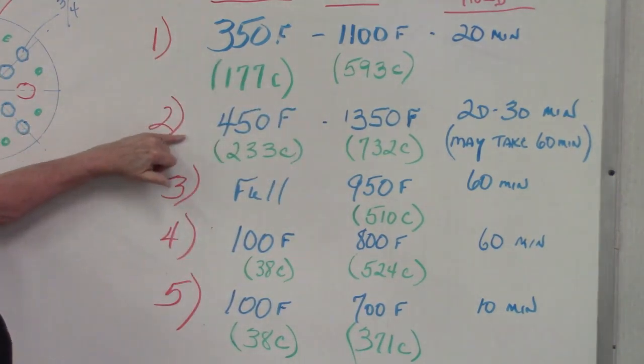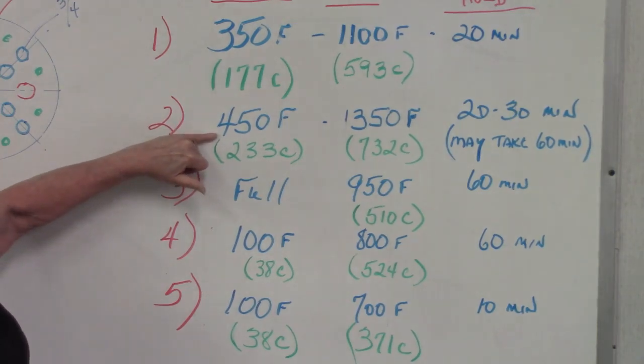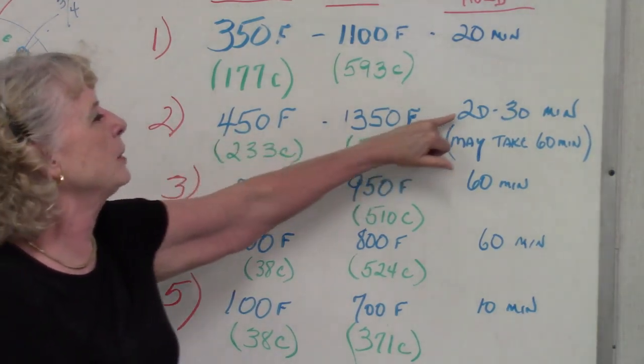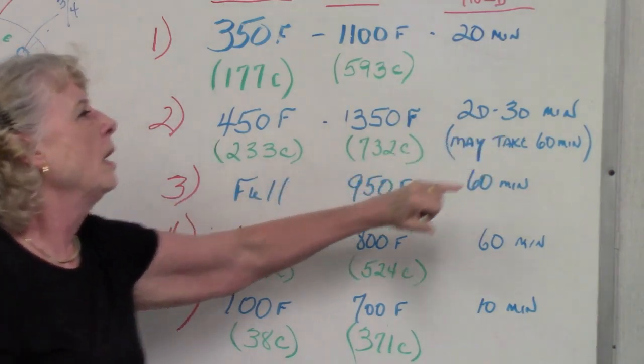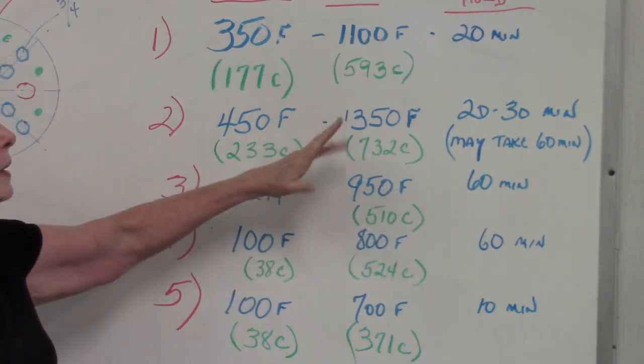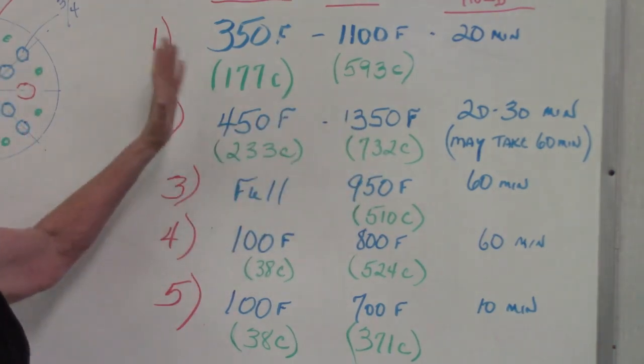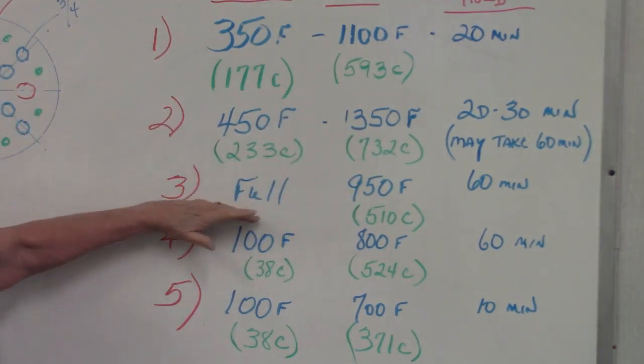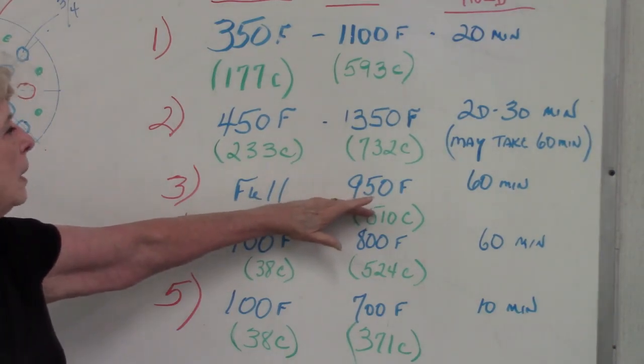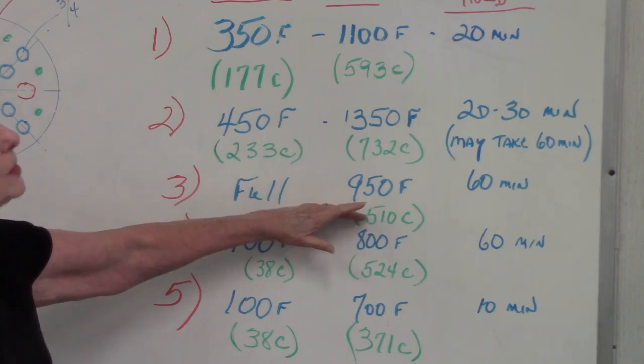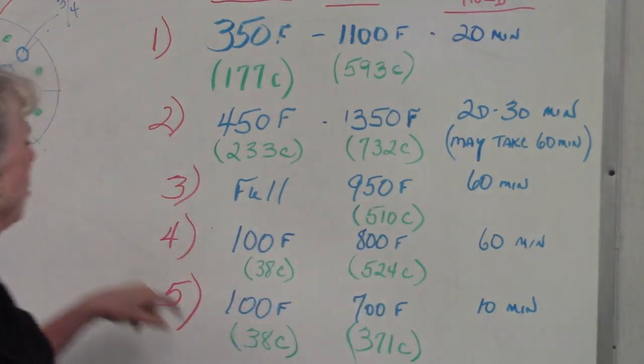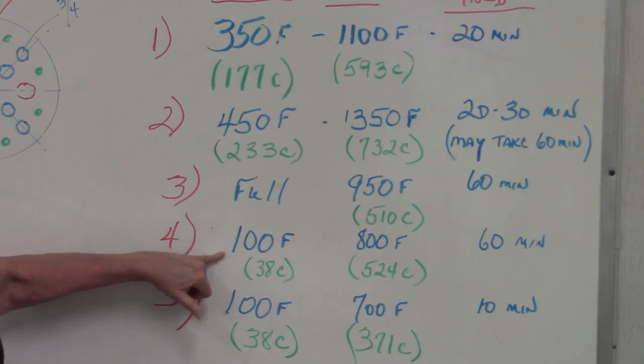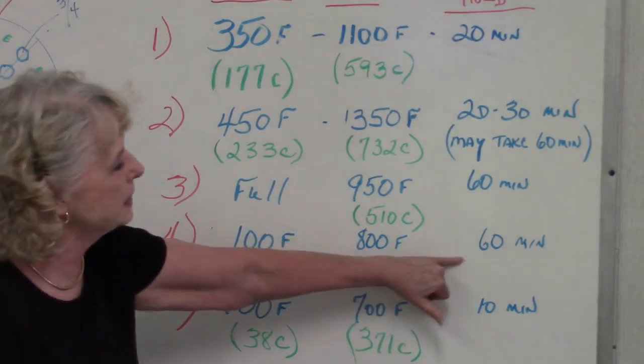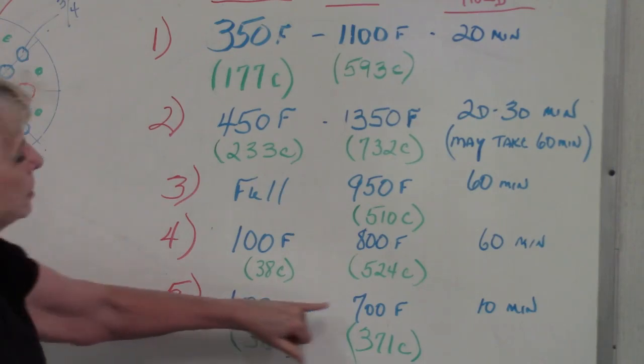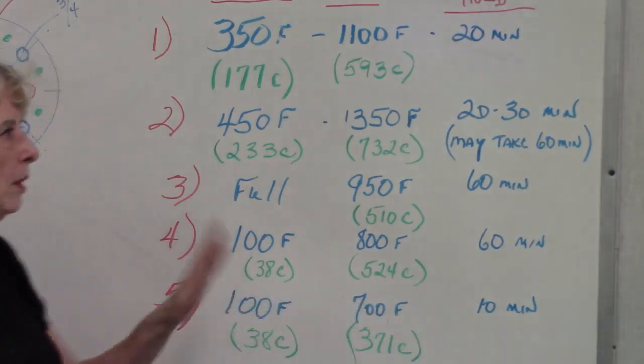The second ramp was 450. I sped it up a little bit to 1350, and I held it for 20 to 30 minutes. It really depended, one or the other. 20 sometimes was not enough, 30 made it. Ramp 3, full to 950. Now this was System 96 glass, so that's the reason it's 950. To use Bullseye, it's going to be different. 60-minute hold, then a ramp of 100 degrees to 800 for 60 minutes, 100 degrees to 700 for 10 and off.